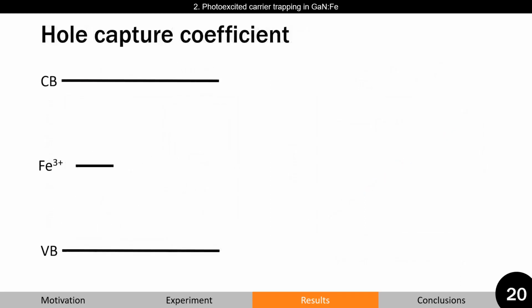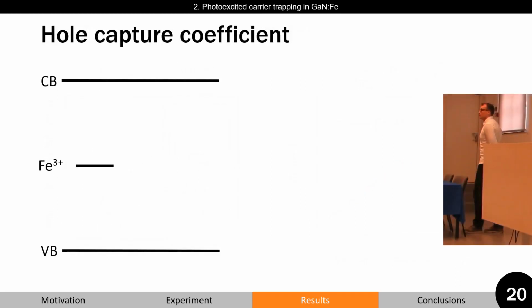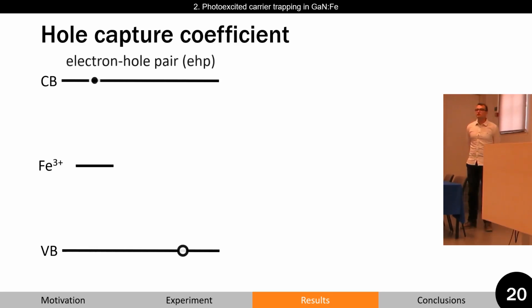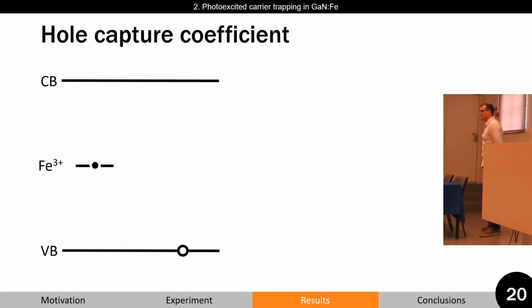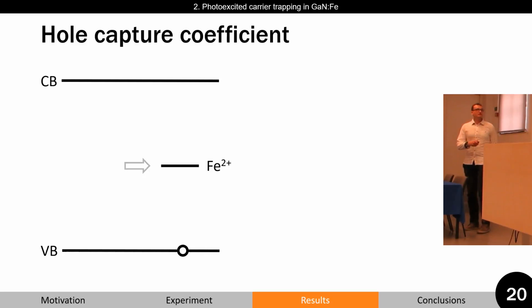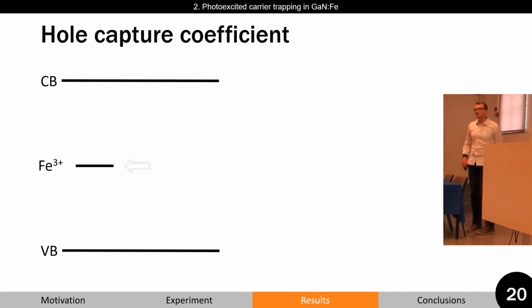Before presenting the Hole capture coefficient, I would like to review the processes during our experiment in slightly more detail. As mentioned before, prior to photoexcitation, iron is predominantly in its 3+ state. After exciting samples with a laser, we generate electron-hole pairs. Electrons can then be trapped by iron 3+, which via charge transfer transforms into the 2+ state, which can then act as a hole trap, and via a reverse charge transfer process return back into the 3+ state.